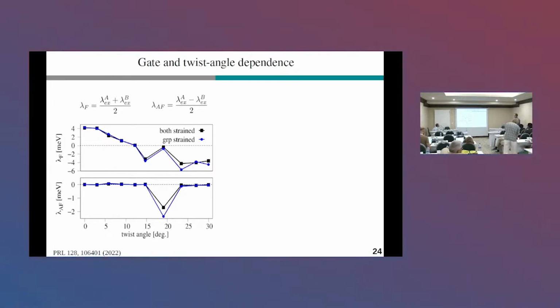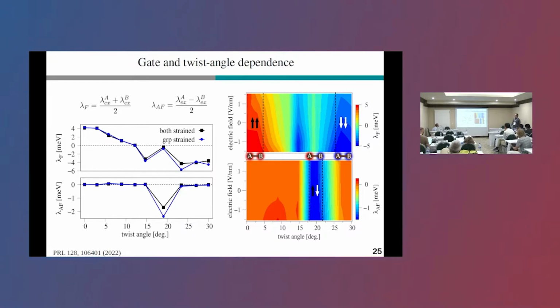However, I have to admit that this antiferromagnetic proximity exchange is not very stable, so it depends very sensitively on the atomic stacking that you employ in your DFT calculations. But still, it's a very nice finding. And of course, we then also checked what the transverse electric field could do. So in these two color maps, I again summarize the ferromagnetic and antiferromagnetic proximity exchange as a function of gating and twisting. And most important is, for example, if you look into this range around 12 degree twist angle, then you can actually switch from positive ferromagnetic to negative ferromagnetic simply with the gating. So you can barely see this in this color map, but still this is a very nice finding that simply with the electric field you can switch the proximity exchange from positive to negative in graphene.